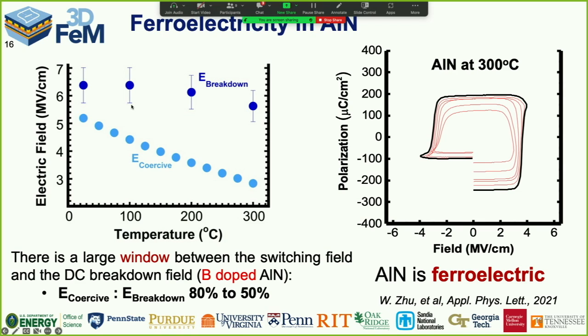And so what we find is that you see that data plotted here. So here's the coercive field, here's the breakdown strength. As we get hotter, we actually get a little more room between where the material flips and where it blows up due to dielectric breakdown events. And that's really cool because we've taken aluminum nitride itself. I taught for 30 years that aluminum nitride is a polar, non-switchable material. And I was wrong. And isn't that fun? That you heat the material up, you change the energy barriers just enough, and even materials that we thought of as never being potential ferroelectrics become ferroelectric. That says that first model of starting with a polar material and engendering a ferroelectric instability, the ability to reverse it, is a viable way of making new ferroelectrics.